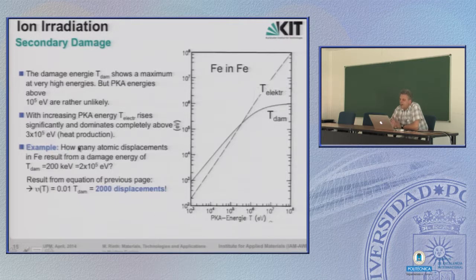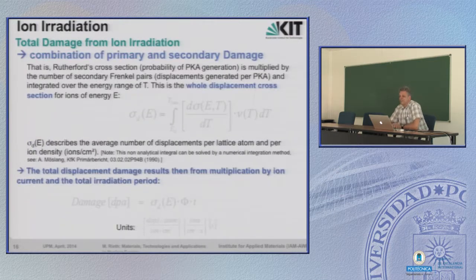An example: how many atomic displacements do we see in an iron lattice as a result of a damage energy of 200 keV? As said, we have to divide the damage energy, that's the 200 keV, by 100, or multiply by 0.01. So with a 200 kilo electron volt damage energy of an incident particle, PKA, this results in 2,000 displacements. This produces 2,000 Frenkel pairs. You are with me? Yeah. Okay. Then let's go to the next step.